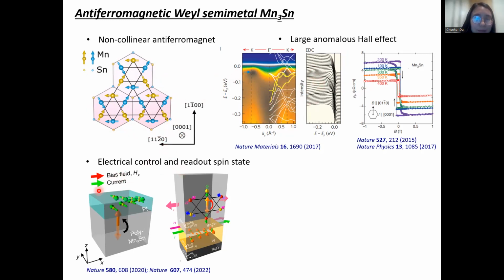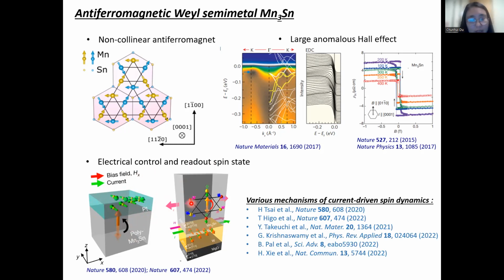And in addition, another exciting research direction is that people find that we can electrically control and read out the spin state of the Mn3Sn by sending an electrical current to the heavy metal grown on top of it. So we can read out the switching of the magnetization from variation of the anomalous Hall effect. There is ongoing research to understand the mechanism of this current-driven spin dynamics of Mn3Sn. Many mechanisms have been proposed, for instance, spin orbit torque or Joule heating, as well as spin transfer torque. So in our study, we will use the NV center as a local probe to understand the mechanism.